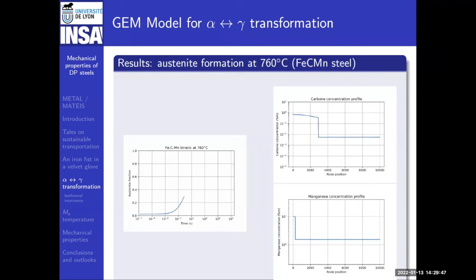So here I plotted the overall transformation kinetics. It's the austenite fraction that you can see evolving as a function of time. And that's fairly strange. So it's during an isothermal treatment. You start at a given temperature, at 750 in the intercritical domain, with 100% ferrite, and you suddenly heat to 760, for which the equilibrium will be 70% austenite and 30% ferrite. And you see that there is this strange evolution.